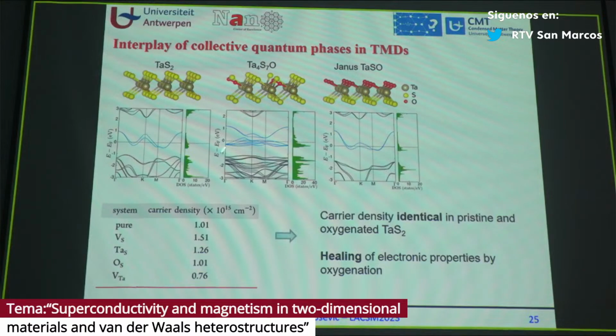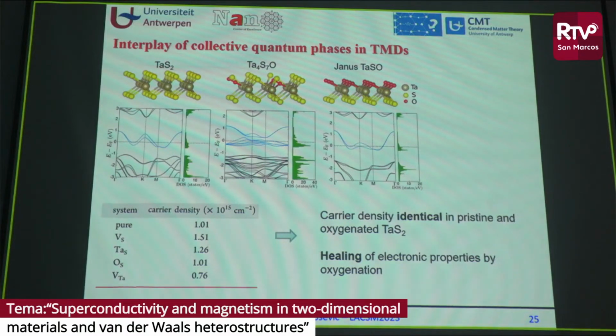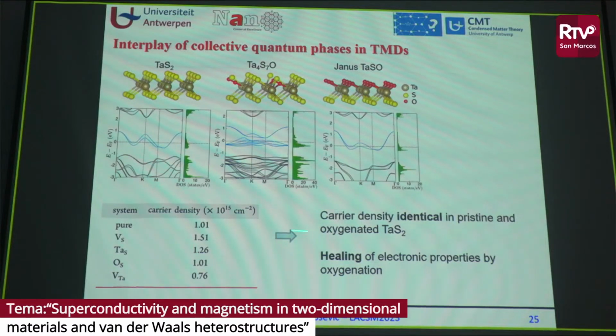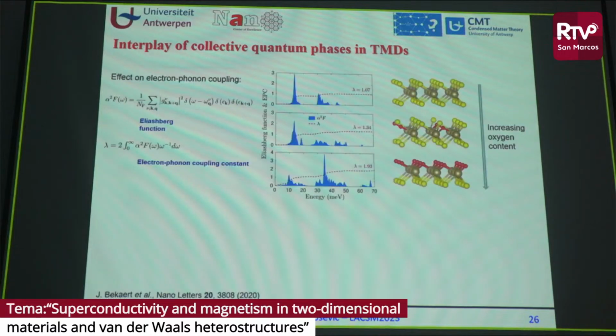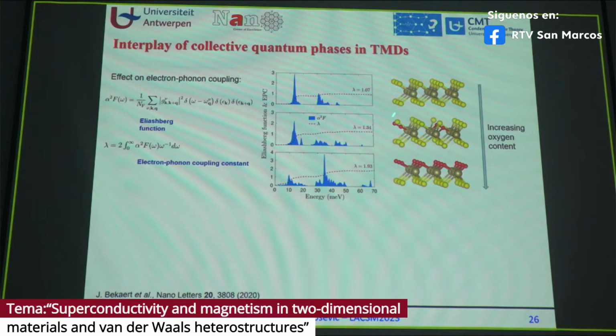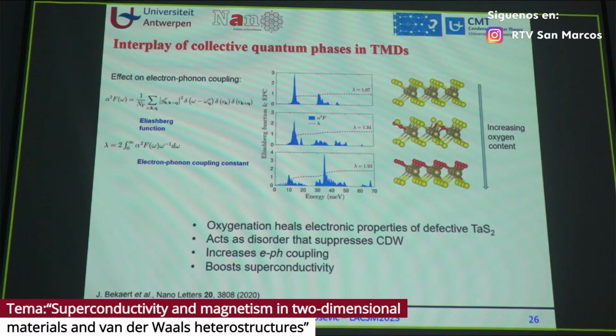And what is very interesting is that the more oxygen we put, we don't see any difference in the carrier density in the material. The oxygen really heals the carrier density in tantalum disulfide, filling in the sulfur vacancy. So we have healing of the electronic properties. The carrier density is identical in pristine and oxygenated tantalum disulfide. So if we continue calculating the electron-phonon interaction, you see that the electron-phonon interaction lambda increases as we increase the oxygen content in the material. These are the red. This is a pure Janus, so one whole side of the material is oxygenated. And the critical temperature doubles in this process. And that's part of the reason why this aging effect, which was reported in Manchester, is actually related to oxygenation.